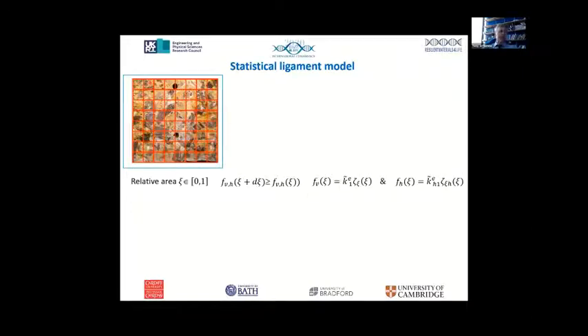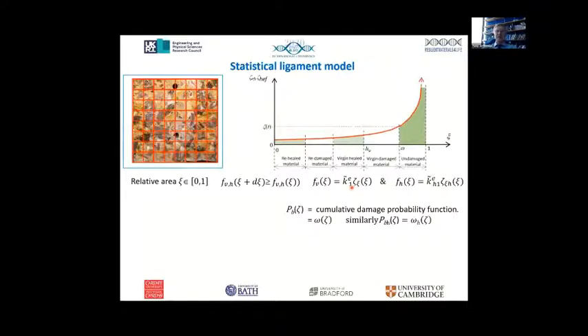So, instead of 100 or 64, I've gone with a chessboard, 64 there. If you imagine that's a few thousand, and you break this into units and you range the strength of those in the order of strongest to weakest, with increasing xi, and then we relate that to a relative displacement parameter through a stiffness. So that gives us a kind of statistical model.